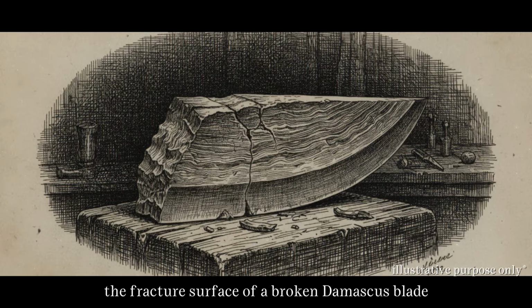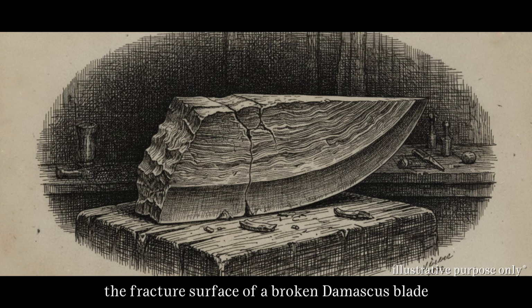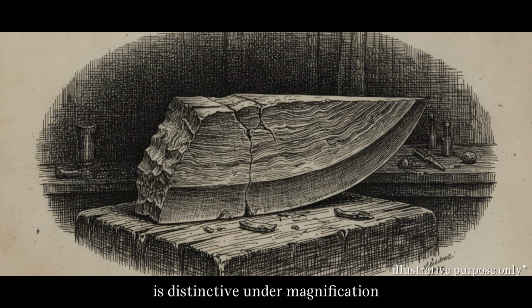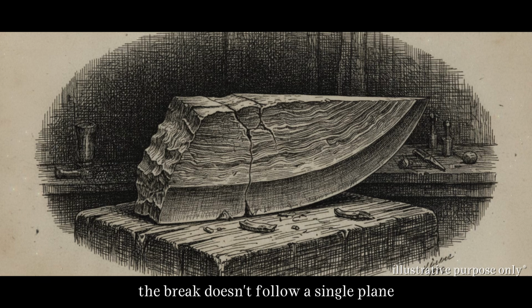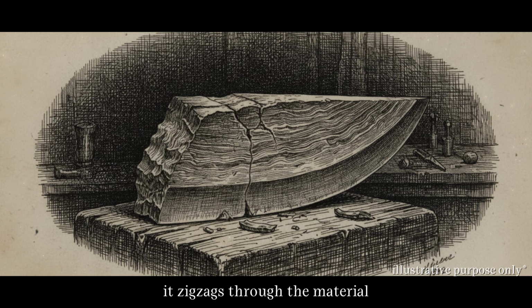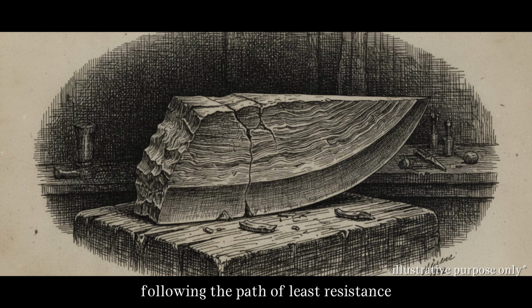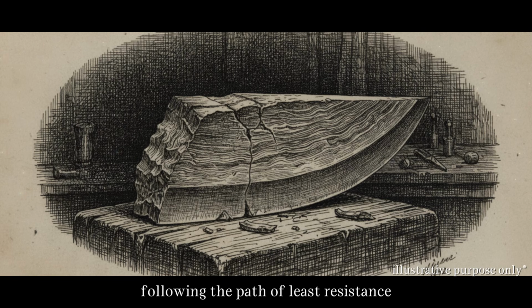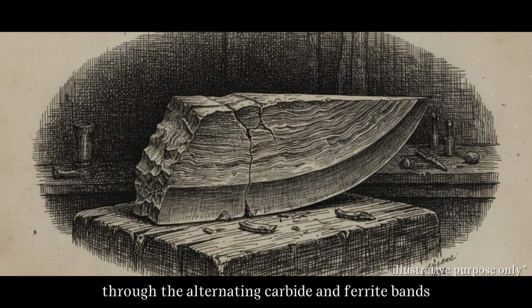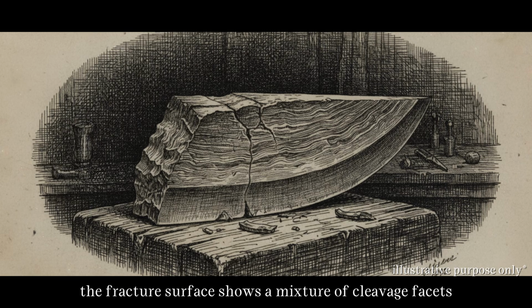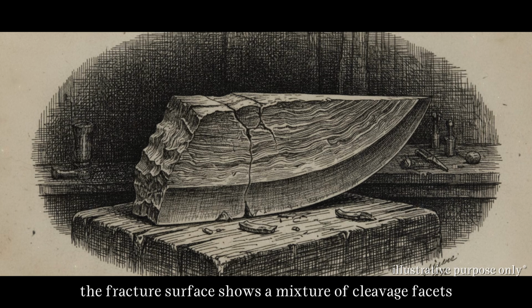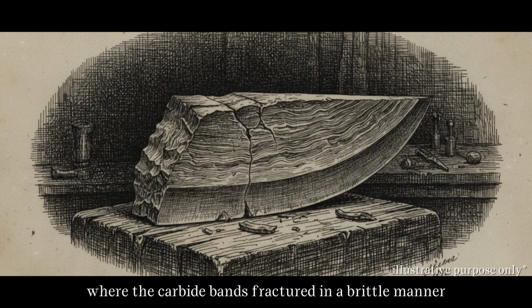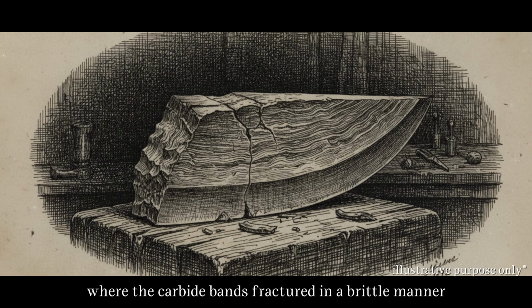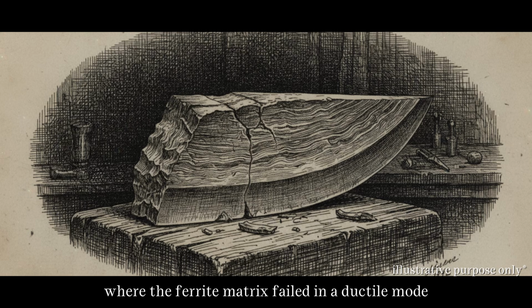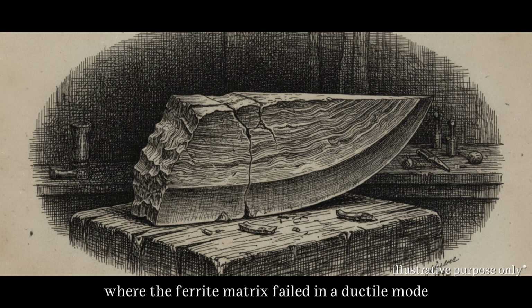The fracture surface of a broken Damascus blade is distinctive under magnification. The break doesn't follow a single plane. It zigzags through the material, following the path of least resistance through the alternating carbide and ferrite bands. The fracture surface shows a mixture of cleavage facets, where the carbide bands fractured in a brittle manner, and dimpled regions where the ferrite matrix failed in a ductile mode.